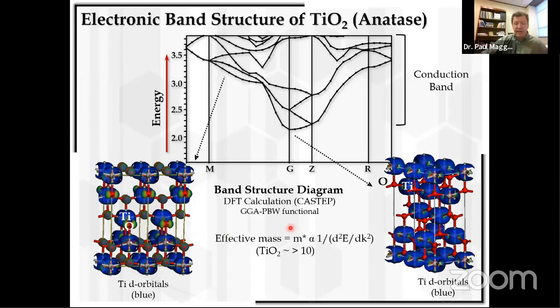The effective mass of an electron in that band is proportional to the second partial derivative of energy with respect to k in k-space here, right? So the more dispersed that band is, the lower the effective mass. That's really great for having high carrier mobility.